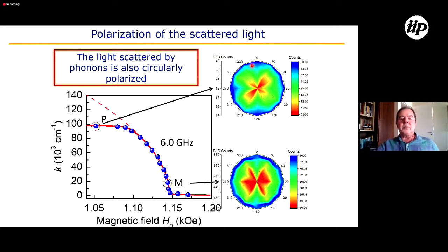And this is quite a surprise because people have been doing light scattering, Raman and Brillouin, by phonons, and phonons are always linearly polarized. But the difference is that here we are doing light scattering experiments by phonons converted from magnons. And it turns out that, as I showed in one of the early slides, magnons couple with phonons with some circular polarization. So this demonstrates that phonons can be circularly polarized, so phonons can have a spin.